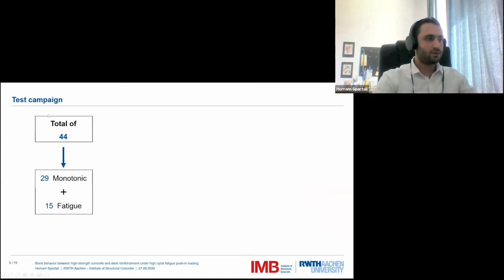Now talking about the testing campaign, we had a total number of 44 specimens, among which 29 were tested as monotonic tests and 15 were tested in fatigue tests. Now, this is not my lucky number or something, 29 and 15 and 44. Actually, this testing campaign is a part of a larger campaign that we are performing at our institute, and the results of the rest of the experiments will be available later when they are finished.